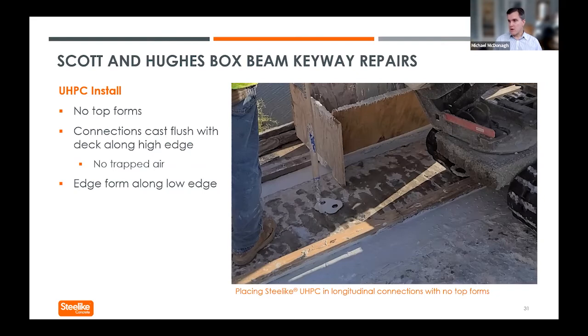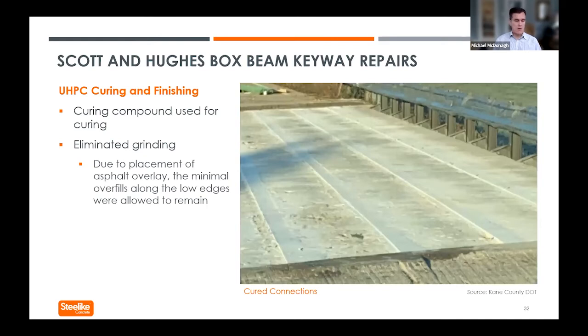Now, in areas where there was differential deflection, maybe between beams, or the cross slope was too high, an edge form was put down at the top. But because these bridges had overlays, the owner saw that the overfill was very minimal, and the owner accepted not grinding, saving the contractor significant time.